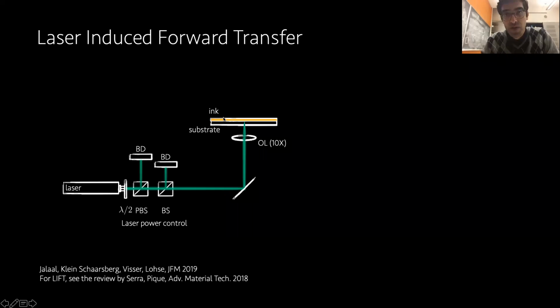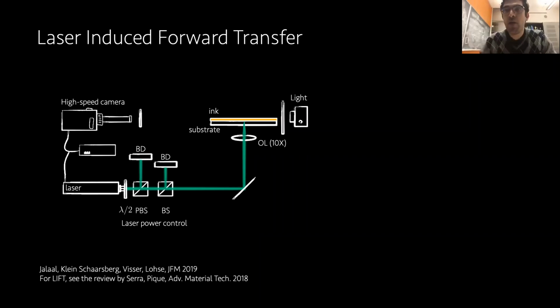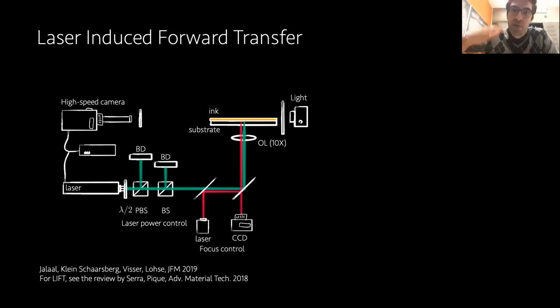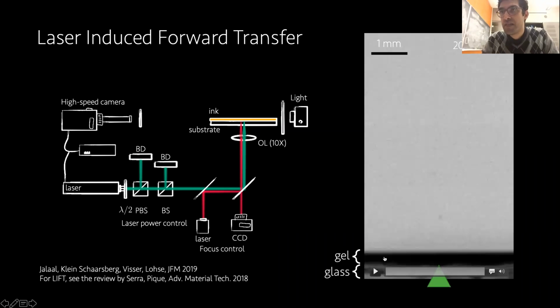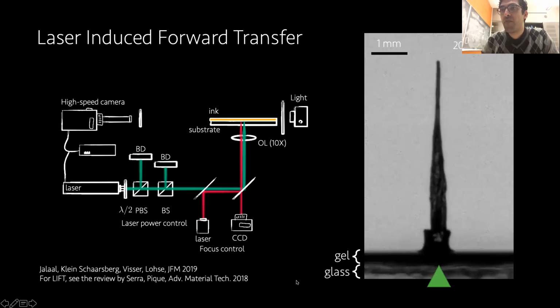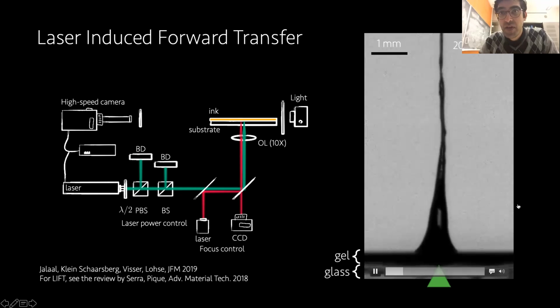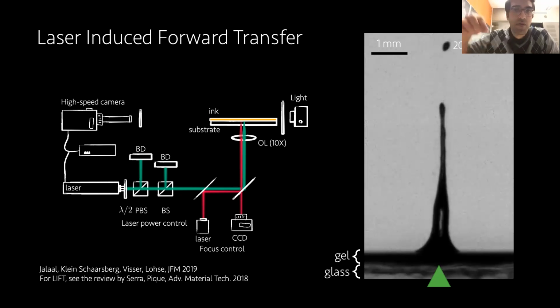And what we also did is add units of optical systems to control the power of the laser. We have high-speed imaging now to look at what happens after we shoot the laser. And we also had another optical unit to control where we focus the laser in this thin film of viscoplastic fluid. This is what happens. This is my Carbopol solution now. This is glass. I shoot the laser and I form this jet. So the idea is, if I could control this jet, I can use it like what you do in inkjet printing or extrusion printing, and print with the droplet.